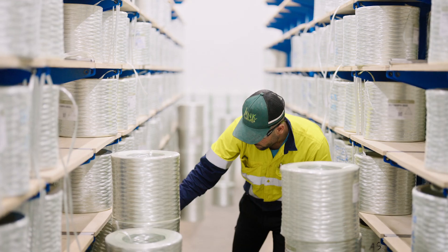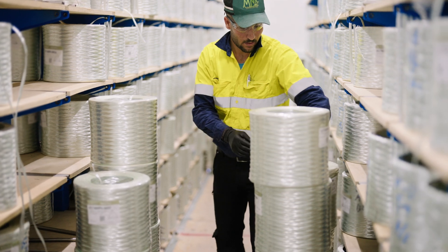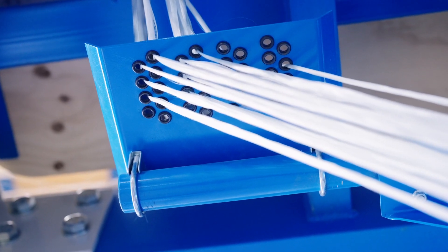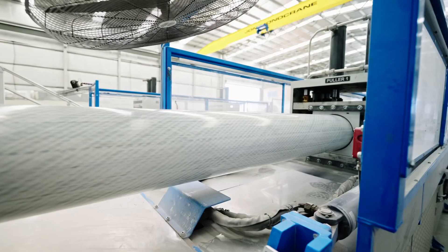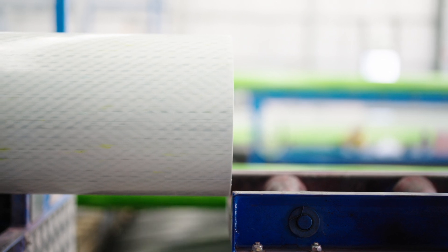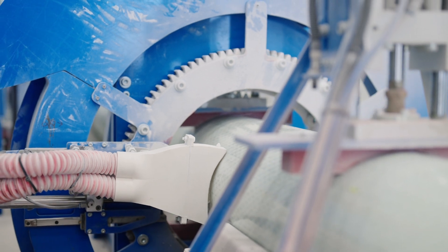The process of manufacturing a utility pole at Wagner's starts with the pull winding, where the glass is laid up onto a mandrel and gets pulled through our glass room out into the die. We use a resin injection process; it passes into the heating die where it's compressed into our final profile and heated to cure the resin, then comes out of the die fully solid and cut off with a saw at the end to whatever length we require.